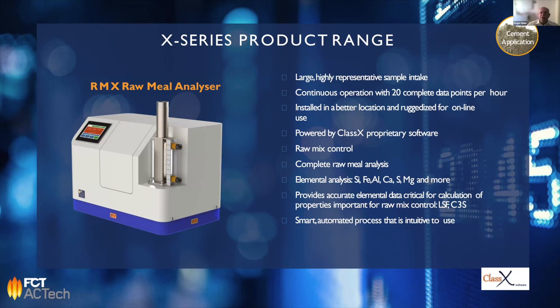Now about the different applications, starting with the raw meal analyzer, which is only XRF, which is suitable to measure all the elements from sodium to uranium. And usually for the cement applications, we focus on silicon, iron, aluminium, calcium, sulfur, magnesium, but also other elements on demand can be discussed to be included. It is a constant measurement, so you get a result approximately every 3 minutes. We steer the sampler in a way that either we use a bypass system or we switch it on and off by looking at sensors, so that we always have fresh material in the analyzer.